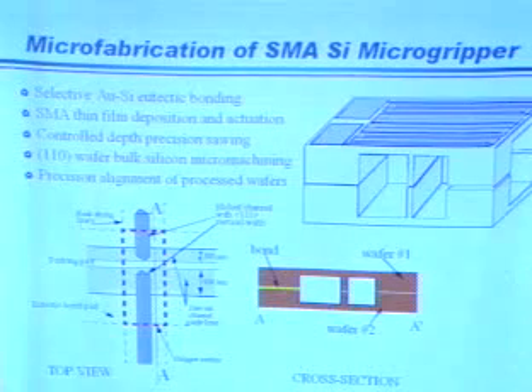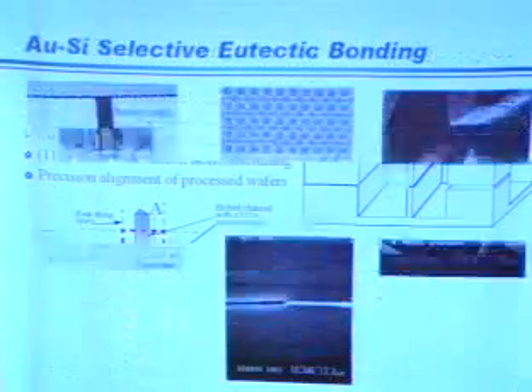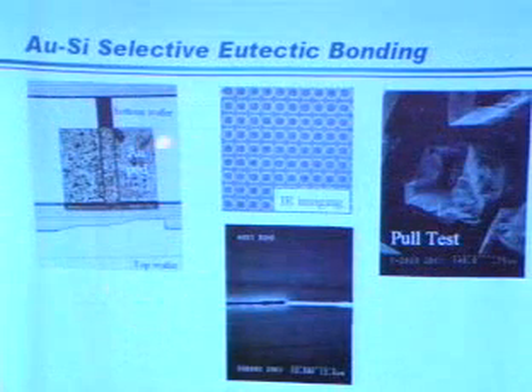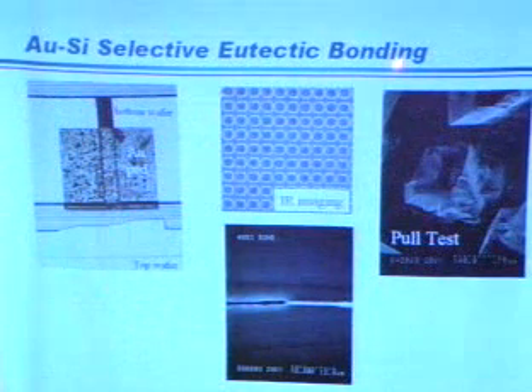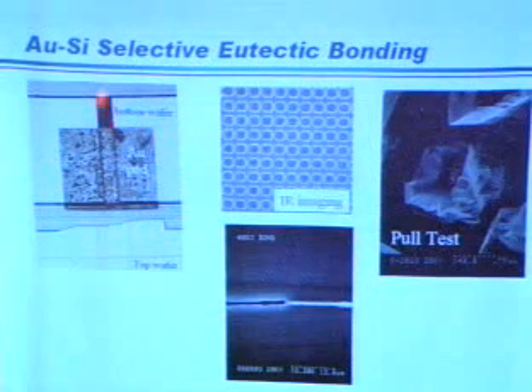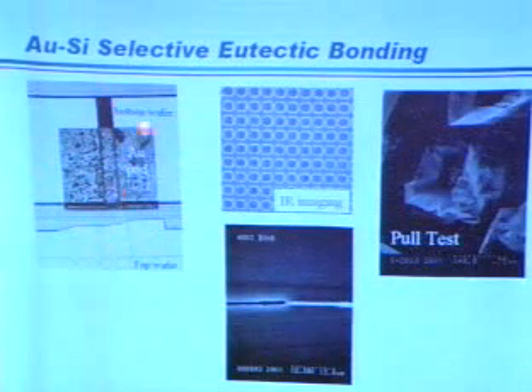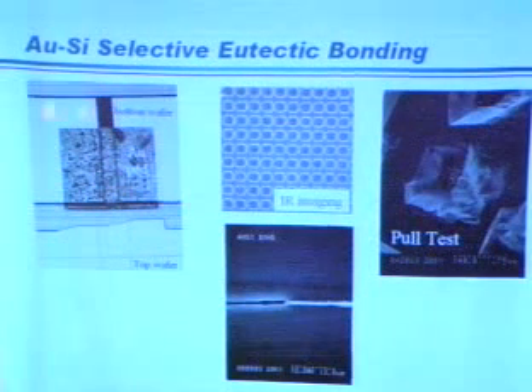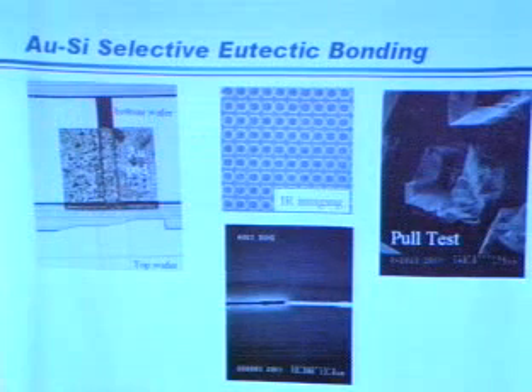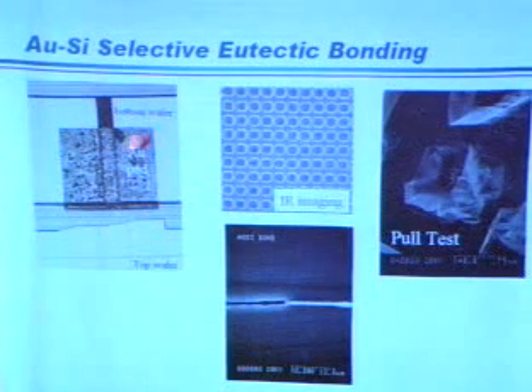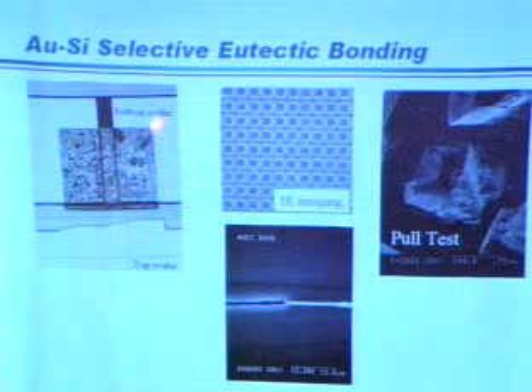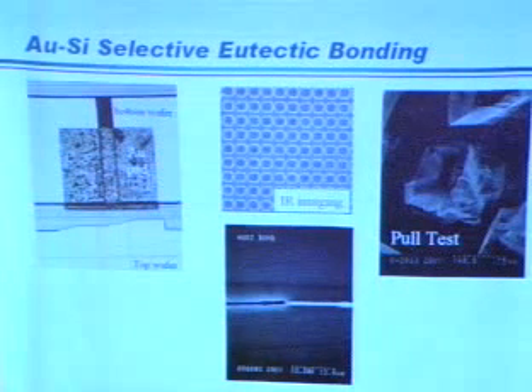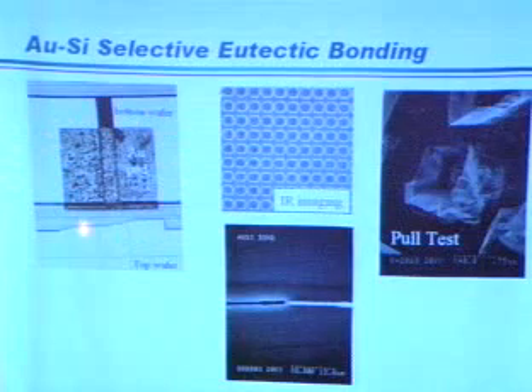And the technologies that we had in several papers we had to go through to get to this point. This just shows one part of the development, how we did the selective eutectic bonding, basically putting, and this is the top wafer here, but we put the gold on, and again, a lot of control is needed here because the eutectic point will change drastically if you have oxygen exposed to it. The eutectic point shifts dramatically, so you don't get the true eutectic effect. But here shows the results.